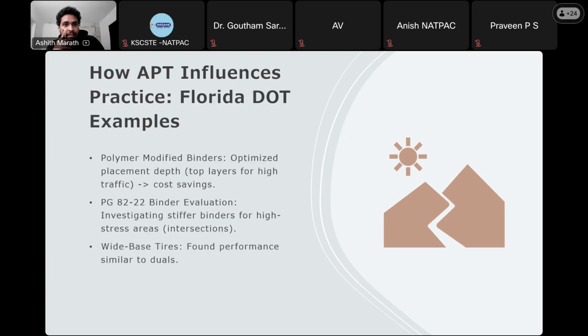And the Florida DOT has done some interesting studies with their APT. They tried to use different polymer modified binders in the pavement to optimize the placement depth. They also did the PG 82-22 binder evaluation, investigating stiffer binders for high stress areas, such as intersections. And instead of the pavement material side, they also tried different tire configurations, evaluating wide base tires against the dual tire assembly. Wide base tires are replacing the dual wheel assembly because of the lesser weight, and they can carry almost the same load as the dual wheel assembly. They evaluated the impact of the wide base tires and found that it is a similar impact to that of the dual wheel assembly.